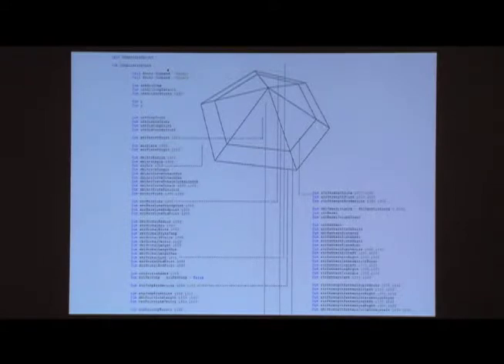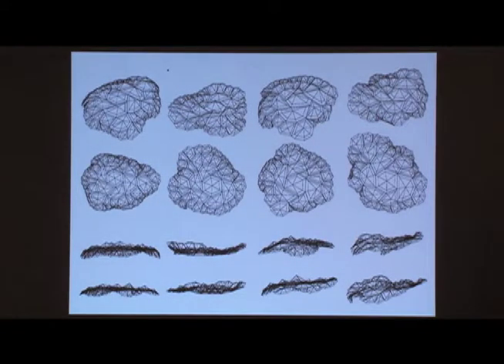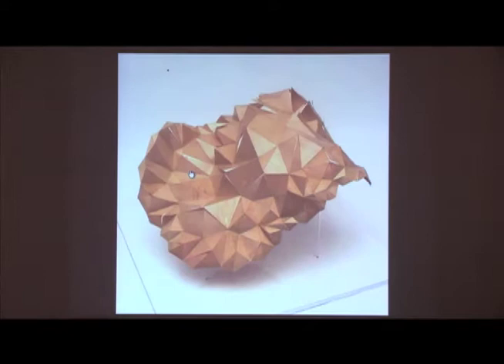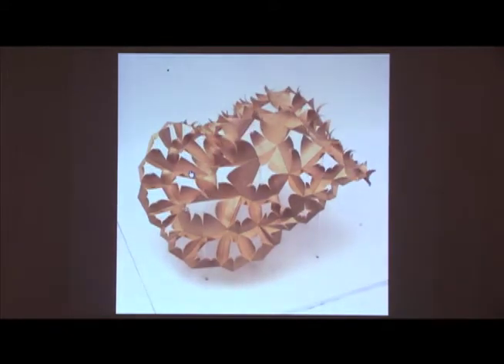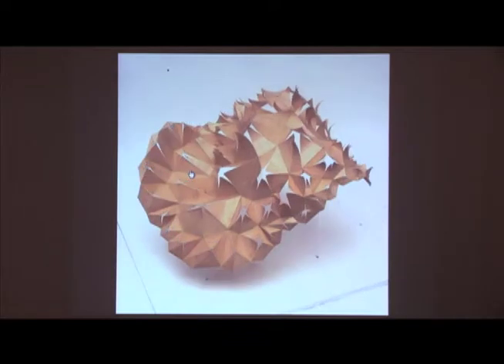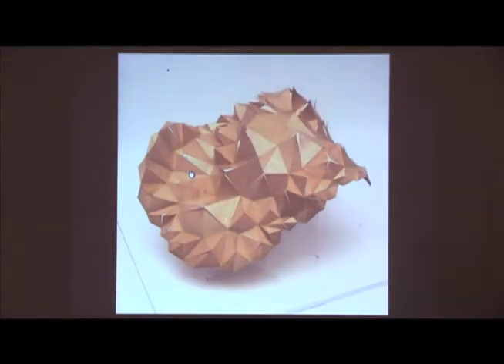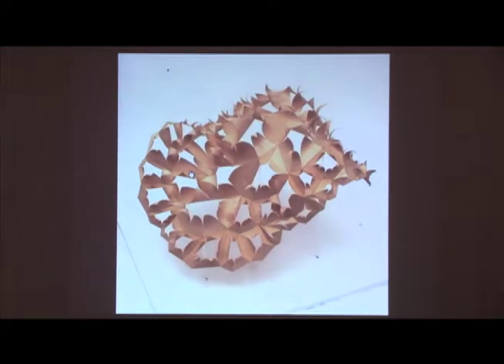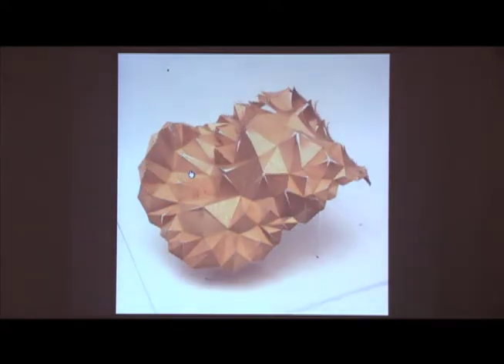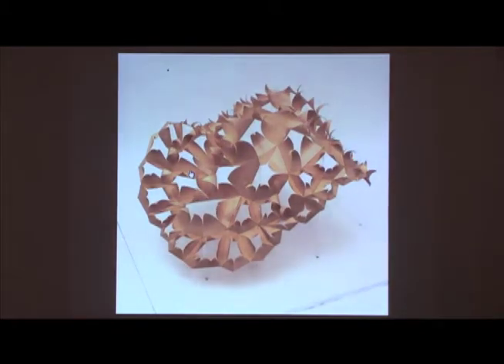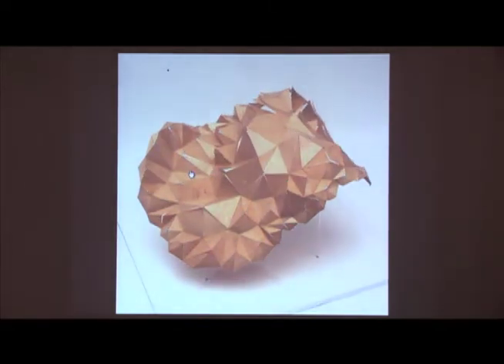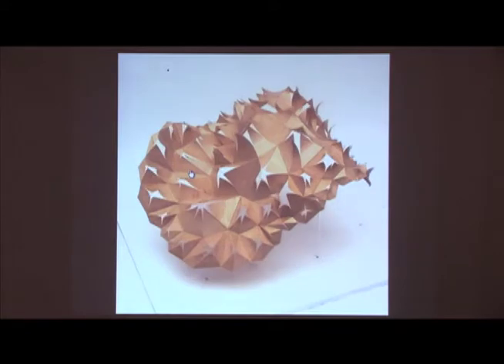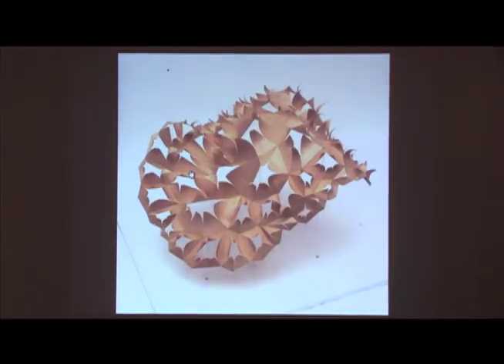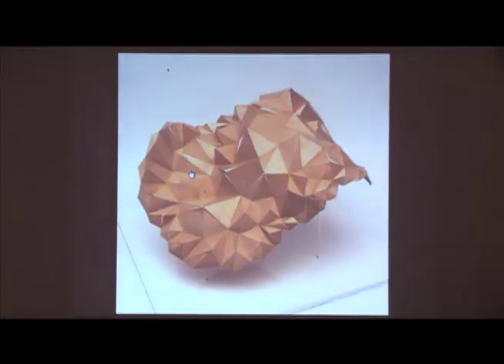And that is now embedded in an adaptive shape algorithm, which allows the use of multiple components. You can see, again, an evolutionary process to achieve this fully functional prototype, accelerated a little bit, so it opens entirely in 20 seconds, given an increase in relative humidity from 50 to 80%, and it takes about 30 minutes to close again. So what you see here is an incredibly simple, incredibly cheap, environmentally responsive system in which the sensor, the actuator, the regulating element, all is just one very simple wood veneer piece.